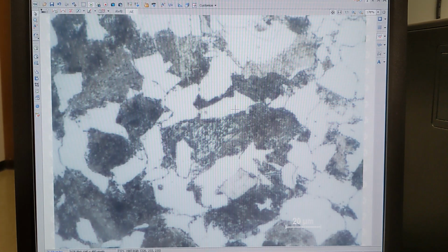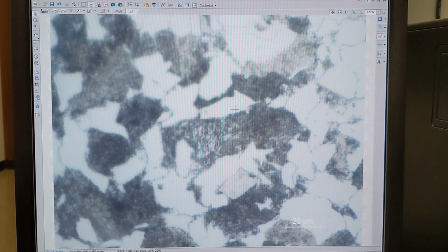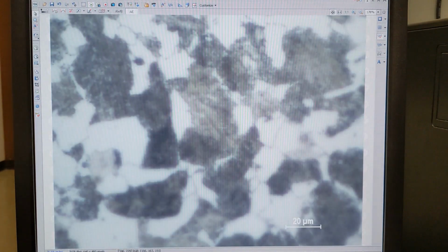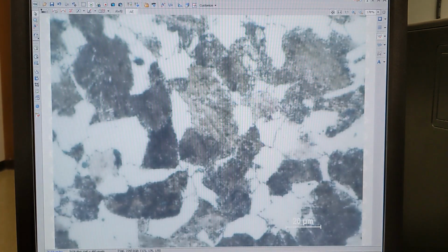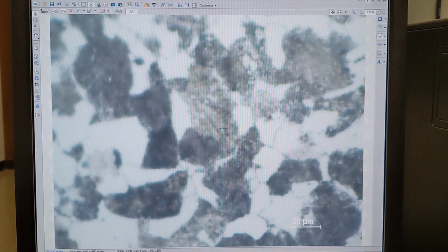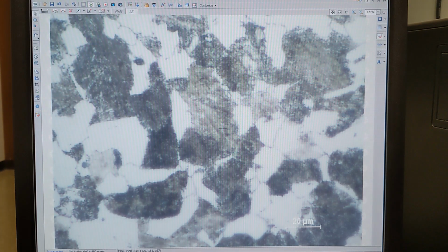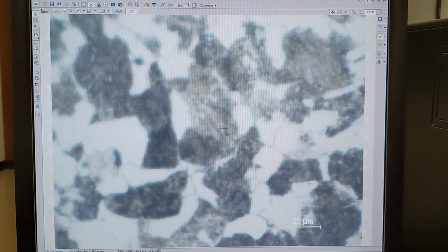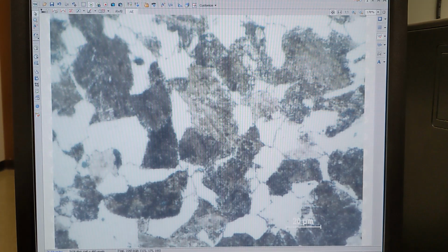at 100 times magnification, which is what we're at right now, you can hopefully see we have some very thin layers, especially in this middle sample here, of ferrite and cementite. We still have the nice grain structure with clear proeutectoid ferrite, which is the light regions, because we are a hypoeutectoid steel. And we have our fine pearlite around. So definitely pearlite, definitely dark regions, but we don't see the big layers that we saw with our 700 Celsius sample.